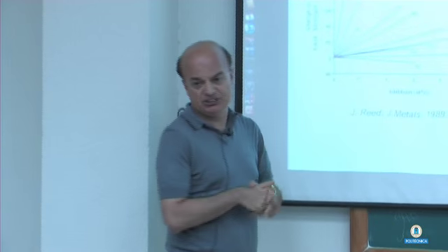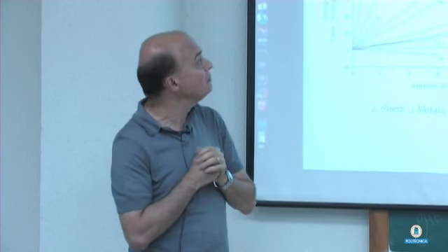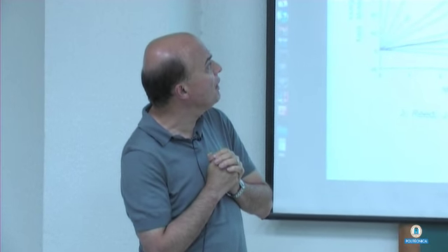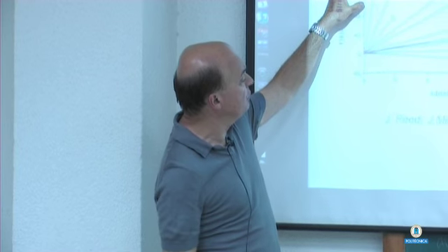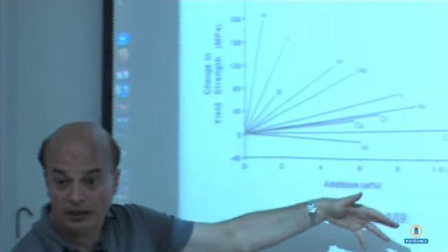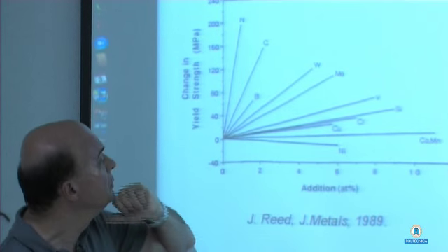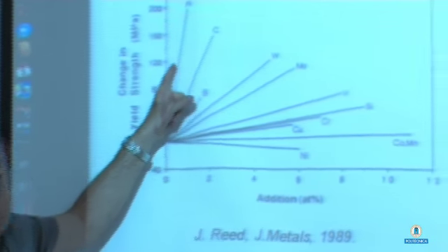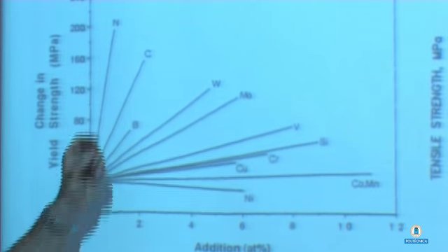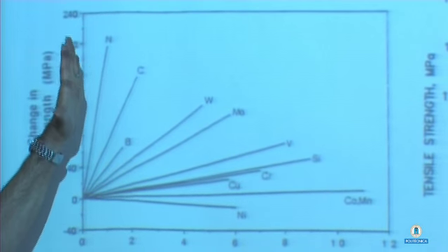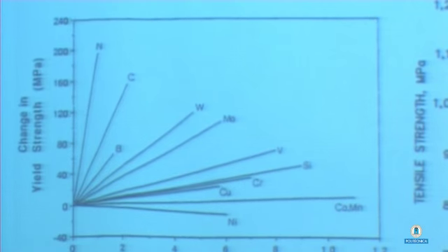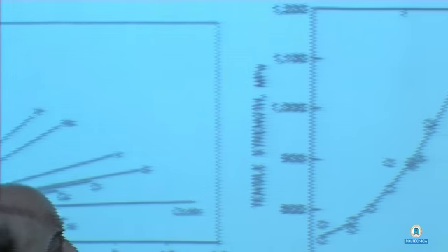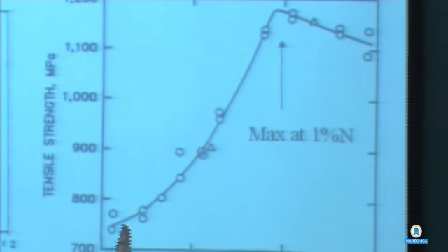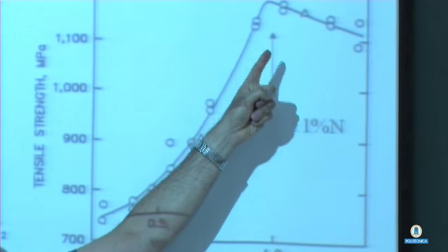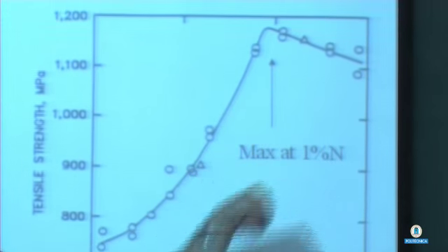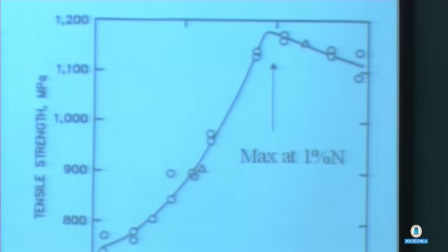Well, if you look at steels, like iron-based metals, we know that if you plot yield stress versus addition of alloying elements, it's again undergraduate information. Nitrogen is very effective as an interstitial in increasing the strength, and it is being used. So you keep adding nitrogen, strength goes up, it reaches a peak, starts to go down, and that peak corresponds to about 1% nitrogen.